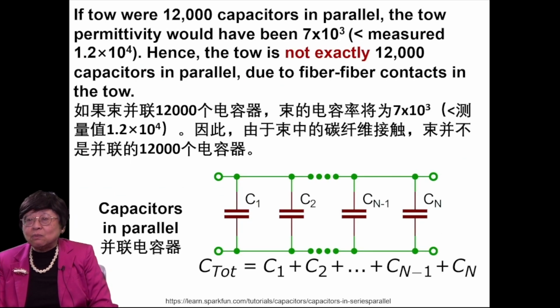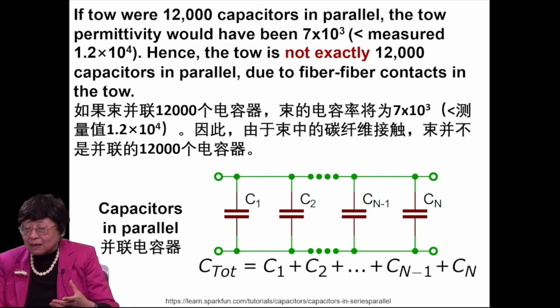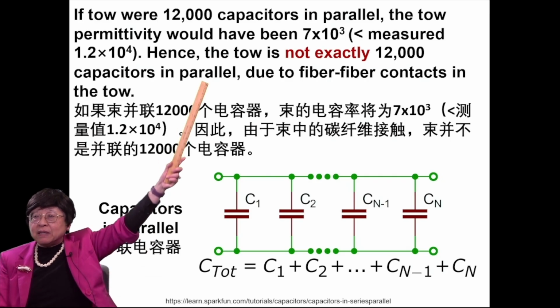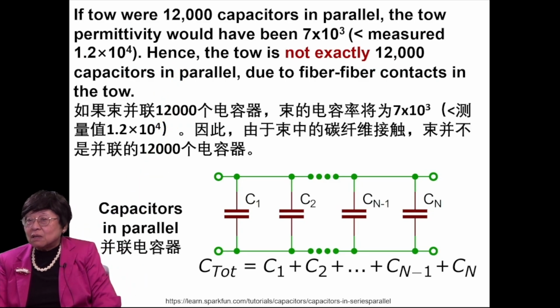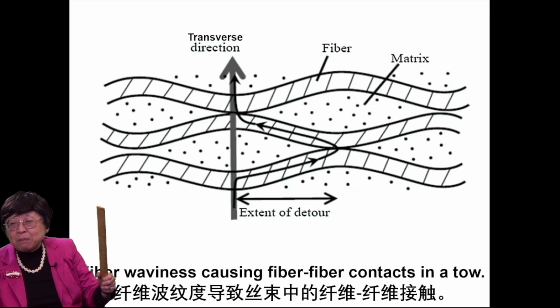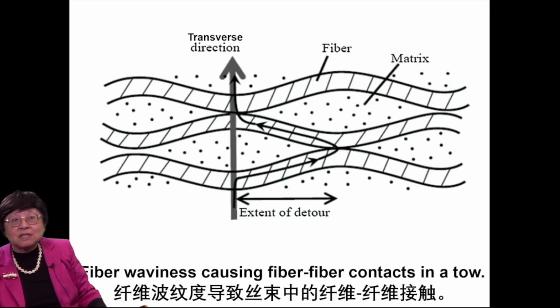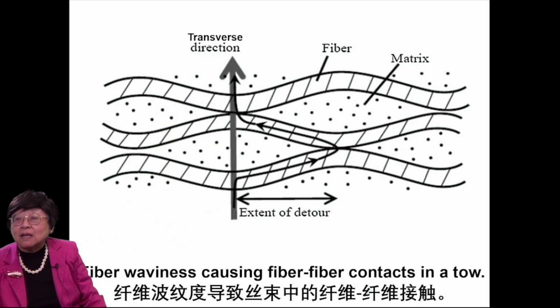Now, if the tow were 12,000 capacitors in parallel, the tow permittivity would have been only 7 times 10 to the 3, less than the measured value of 1.2 times 10 to the 4. That means the tow is not exactly 12,000 capacitors in parallel, due to the fiber-fiber contacts in the tow. And this is what I mean by fiber-fiber contact, resulting from the fiber waviness. This is the transverse direction.